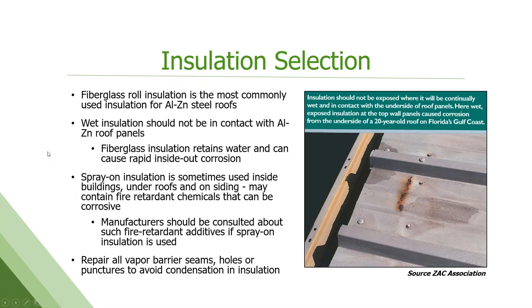And then insulation. Insulation in and of itself is not a problem, but you certainly don't want a situation where the insulation can become wet and stay wet in contact with the panel, because it will cause corrosion. This is an example of a 20-year roof where the way it was designed, water could get into the insulation and was held against that panel, and you can see it's corroded down to the base steel.